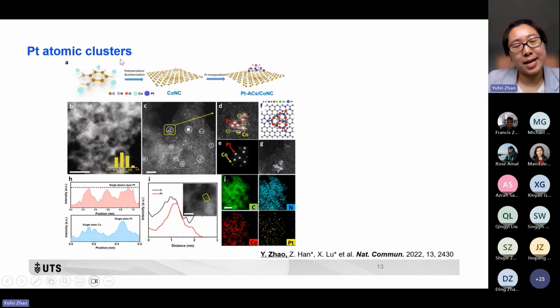For the atomic cluster, as I talked about, the surface free energy is also very high. It's similar to the single atom catalyst. So we need to find a very strong support to stabilize this atomic cluster. Here, the substrate we have found is cobalt single atoms. We have used these cobalt single atoms to stabilize this atomic cluster and form this protrusive structure. This structure makes it easier to interact with the reactant and facilitate the HER process.